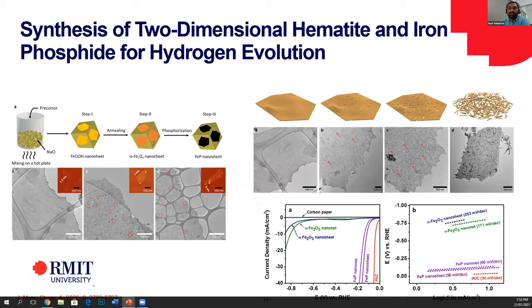So what we then did, on the sheets, we tried to manipulate their surface area. When we get 2D sheets with different structural changes on them, we found that we are creating some porosity, we are creating disorderness in the structure, and ultimately we found that they perform very well. They are approaching the performance of a noble catalyst, and they are very active in their reaction kinetics.